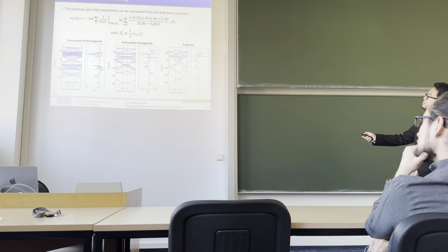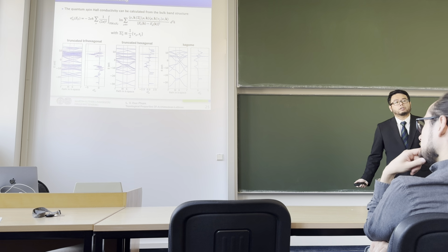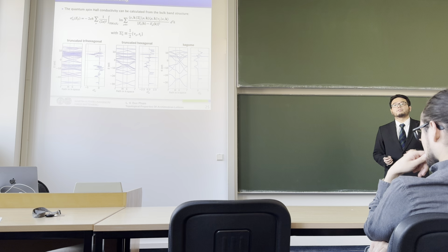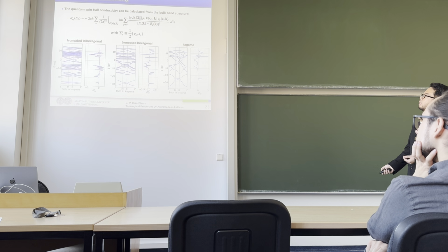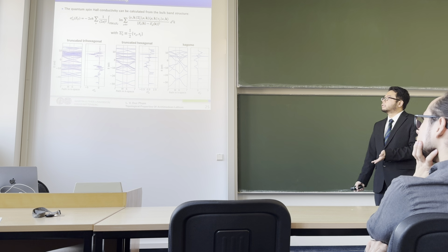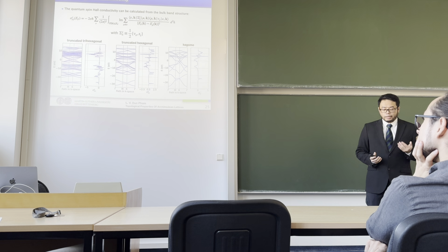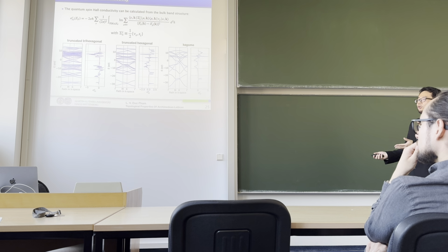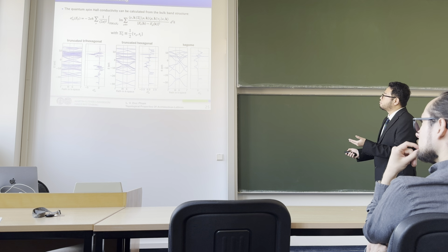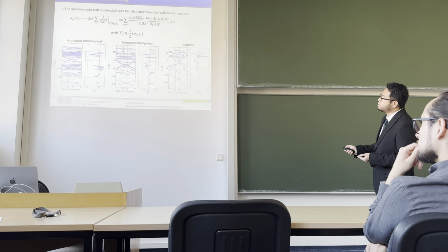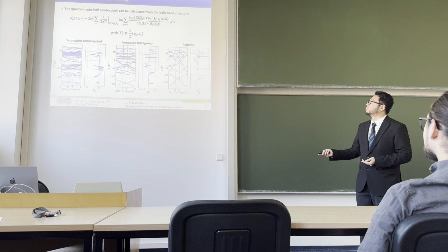And one important feature is that in the denominator you have the square of the energy difference. So the conductivity should be large when the energy difference in the band structure is small. And this is the behavior that we've seen across the calculation that we have over here. For real-world applications, you can shift the Fermi level by applying a gate voltage or by doping. So in order to have good conductivity, you should look for systems that have peaks near the Fermi energy, into which you can shift the Fermi level, so you can obtain large conductivity.